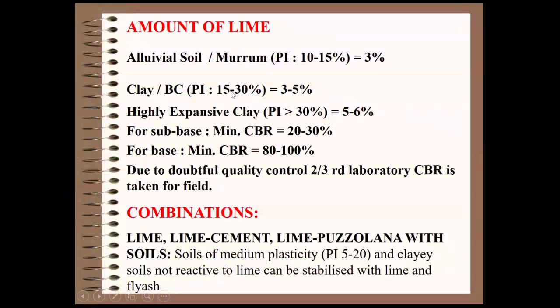For clay or BC soils, 3 to 5% lime is generally sufficient. For highly expansive clay, 5 to 6% is suggested. Again, these are mostly to address the plasticity problems. But then the other requirement is CBR: sometimes a 20 to 30% CBR value we should get after the amendment. This is another problem. Most of the time we may not get this, for which a little higher lime content is required, because initially some 3 to 4% lime will be consumed by the soil to address its own plasticity. Only when the plasticity is overcome will strength come.